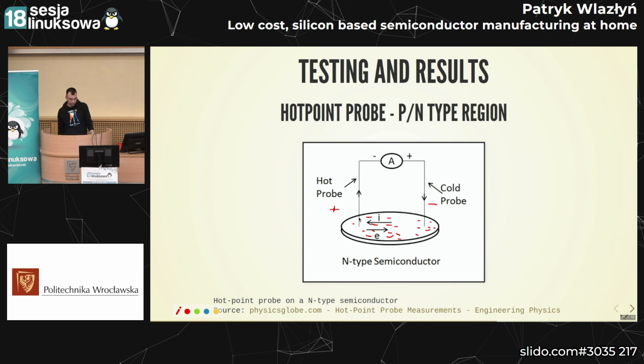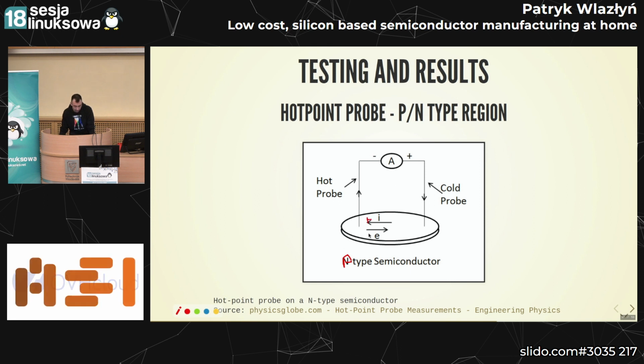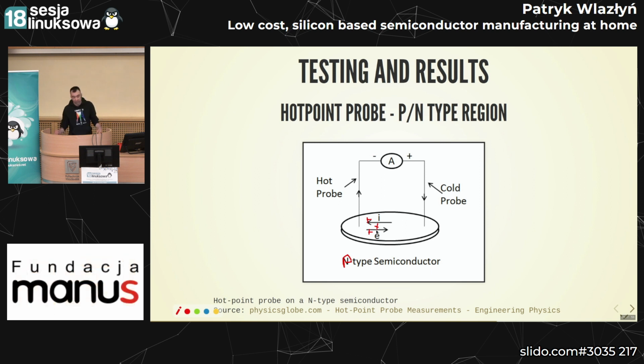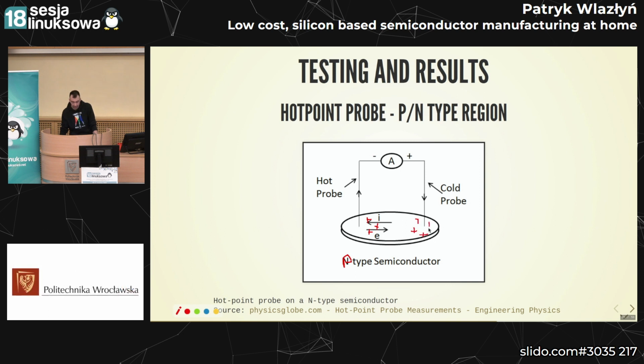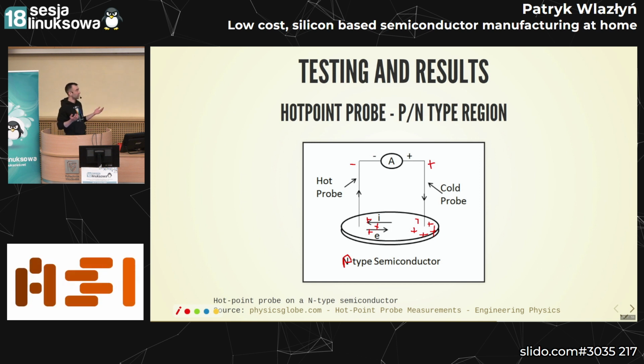And this way we can check that this is an N-type semiconductor. If we do this for a P-type semiconductor, for example, we will have more holes here, so there will be pluses, but the hot probe will expand the material again, pushing away the holes, and it will create more holes on the other side, and it will create actually a reverse bias. So by reading the difference in voltage on a voltmeter, you can determine whether you have a p-type semiconductor or n-type. And so with this, you can determine whether your chemical process worked.